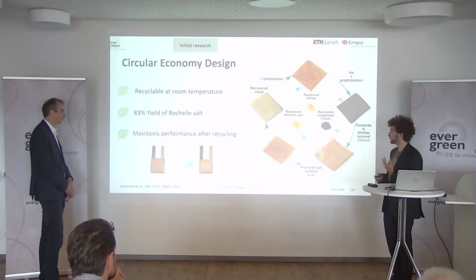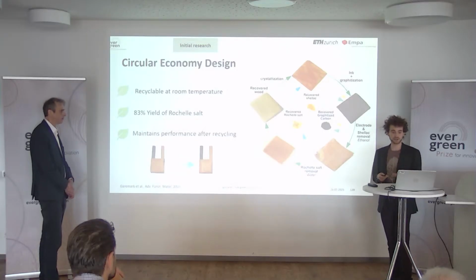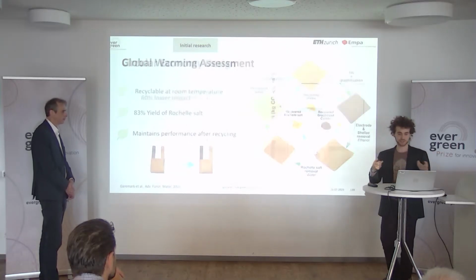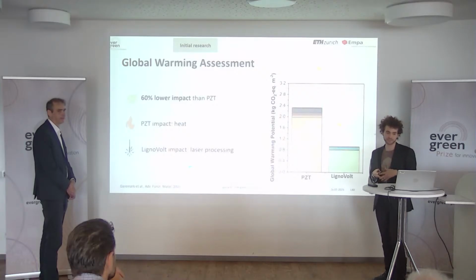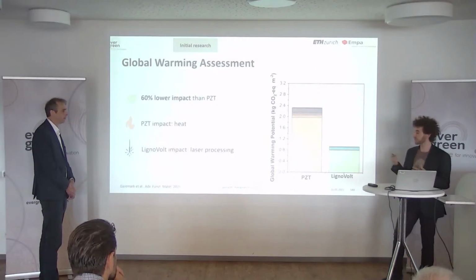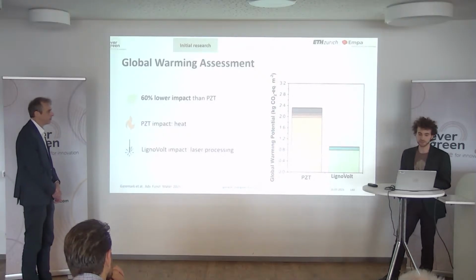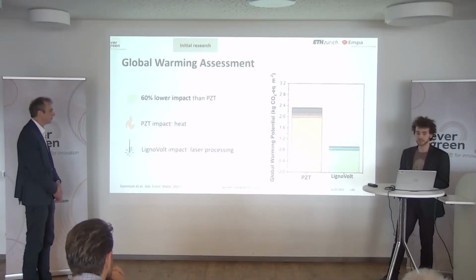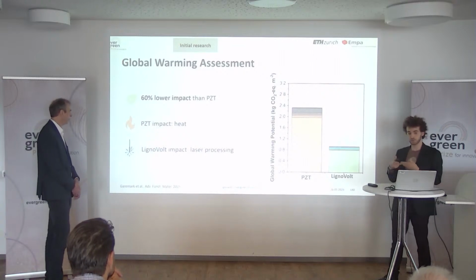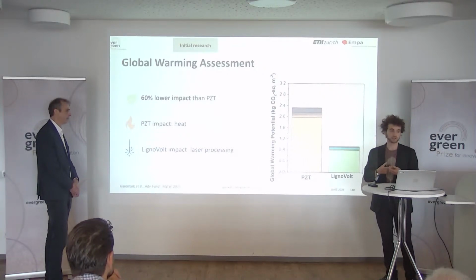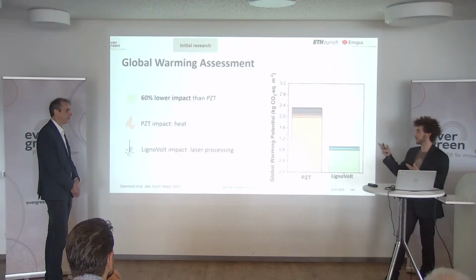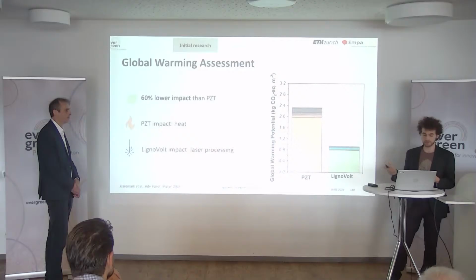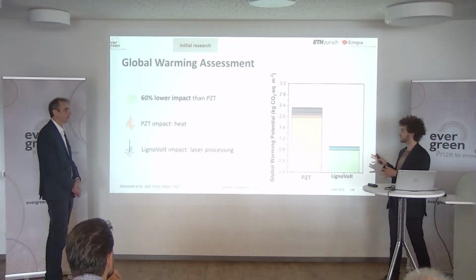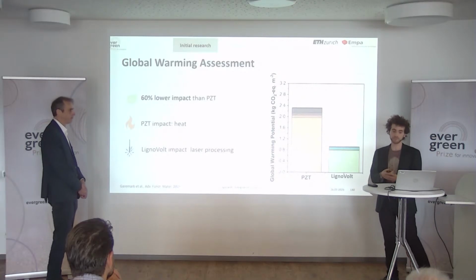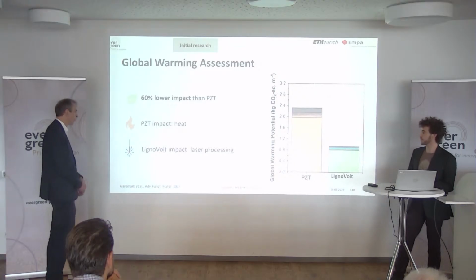And what's very important for me is not only to use natural products, but to avoid so-called greenwashing. So we wanted to look into a global warming assessment. We wanted to look at the CO2 that our product emits and compare it to PZT. In this assessment, we're just looking at the global warming potential, and I want to remark that we're not looking at, for example, the lead components that can be leached from PZT, and also in this assessment, we didn't look at the recyclability of LignoVolt, so this would be just the production step. We had 60% lower impact than PZT.